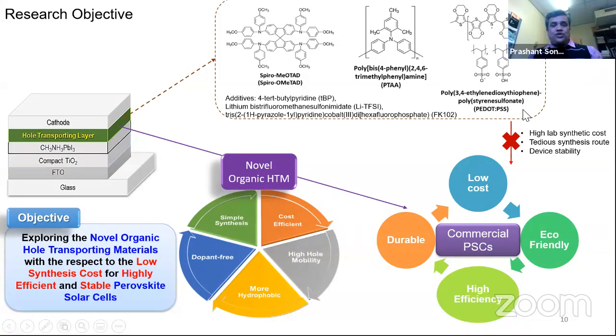And utilizing those PEDOT:PSS and PTAA, the whole system becomes highly vulnerable to moisture, because it is ionic as well as acidic by nature, the PEDOT:PSS polymer and the spiro. So our novel HTM should be low cost, eco-friendly, high efficiency, durable, and, as I mentioned, have a high hole mobility and be dopant free. We do not want to add this lithium type of dopant. We should have a material which can be dopant free.